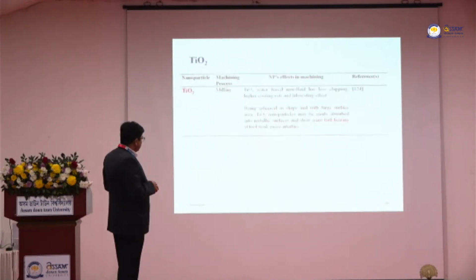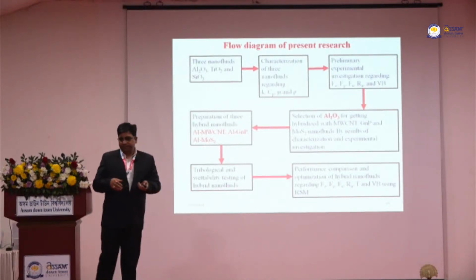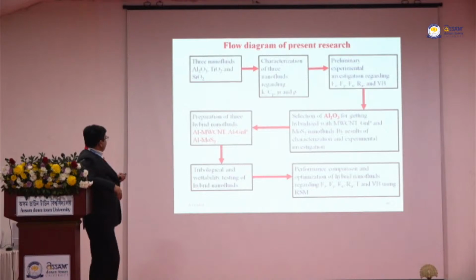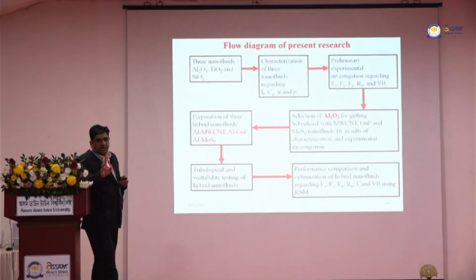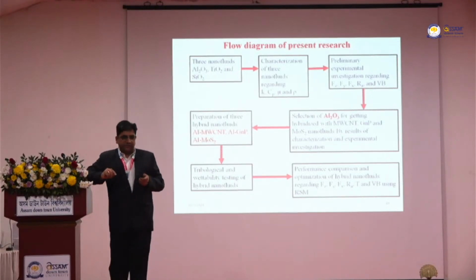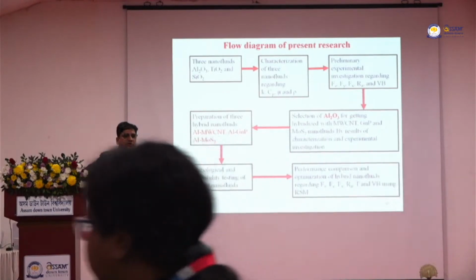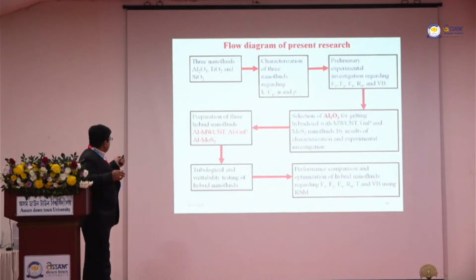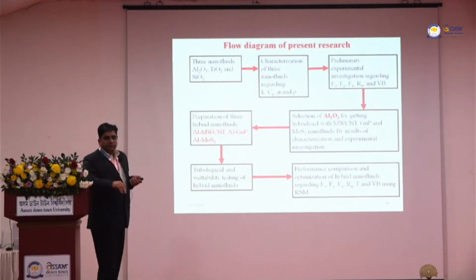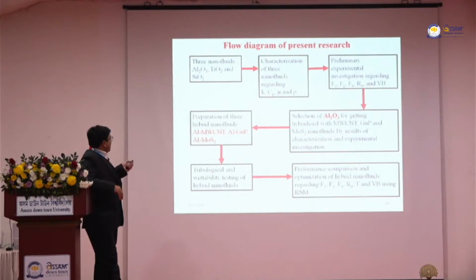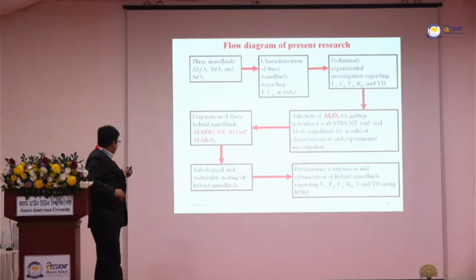So I am skipping all these things. I will just come to the methodology part. So how did we do it? First, we took 3 nanofluids: alumina, titania, and silica, depending upon the properties, because there are 2 important properties which a cutting fluid should possess. First is the cooling property, second is the lubricating property. Titania and alumina have good thermal conductivity, and silica has a good lubricating property. We did a literature review and found that researchers have used a number of nanoparticles, but we found that these 3 can be taken for our investigation.